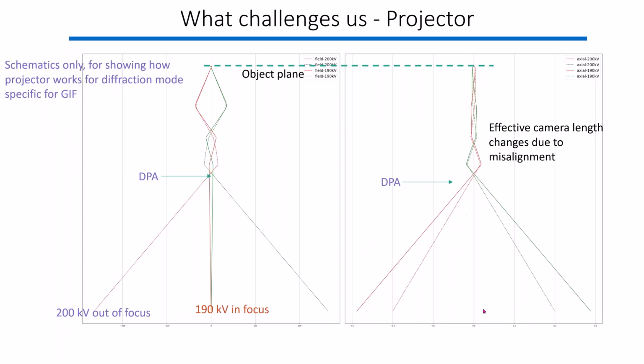And the other thing we have to bear in mind, and this is a practical warning message, is that if you have a misalignment from somewhere, let's say a mechanical misalignment or any other optical misalignment, the effective camera length can change due to this misalignment too. So you really have to take care of the effective camera length and the effective collection angle of the signals, so that you can maximize the output, because the K-shell excitation cross sections are such that you don't have much signal.